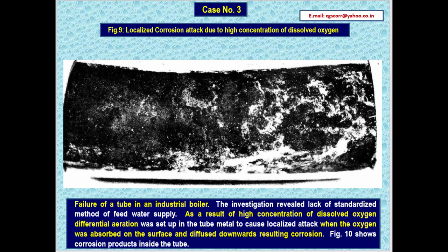Failure of a tube in an industrial boiler. The investigation revealed lack of a standardized method of feed water supply. As a result of high concentration of dissolved oxygen, differential aeration was set up in the tube metal to cause localized attack, when the oxygen was absorbed on the surface and diffused downwards resulting in corrosion. So this figure shows the corrosion products inside the tube.